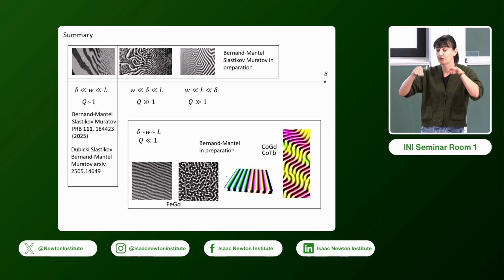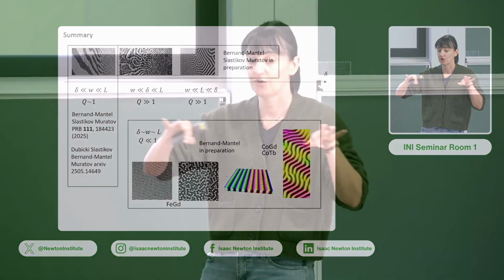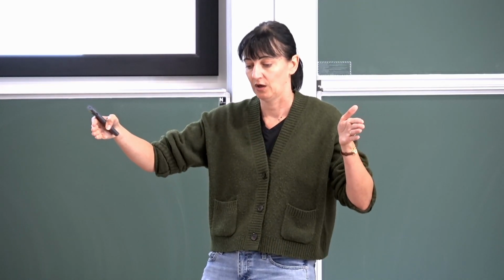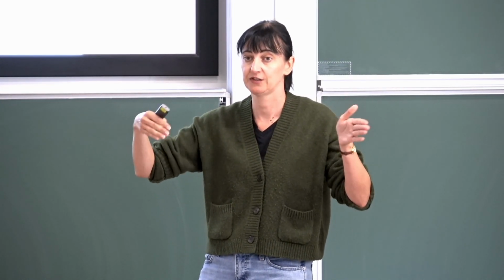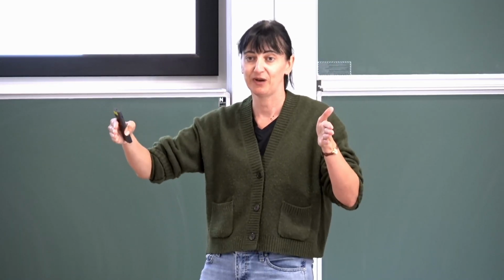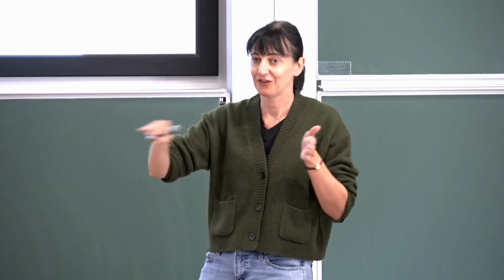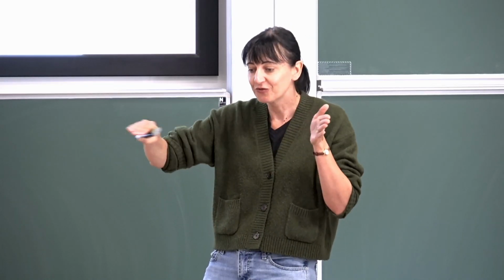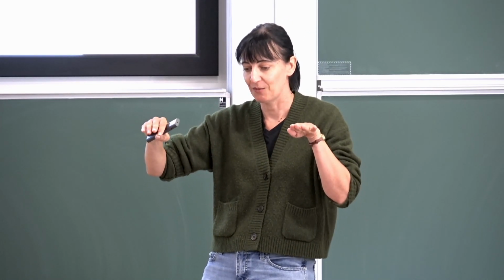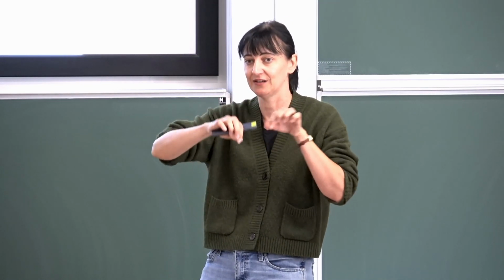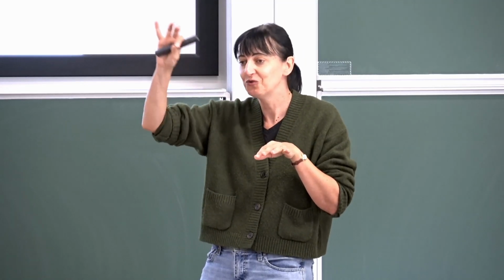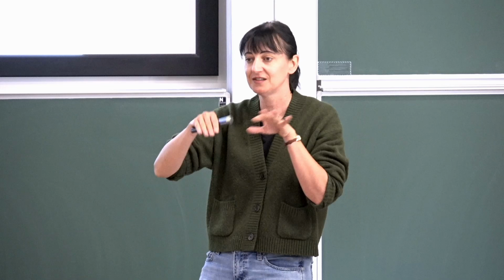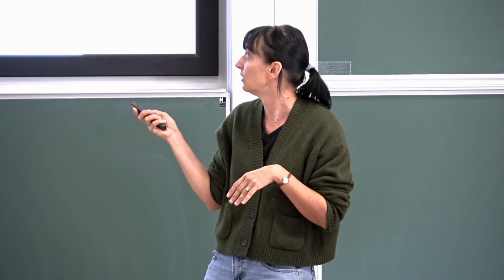But when you have only a few monolayers, there is a lot of disorder appearing because you control the crystallinity in the XY plane. But in the Z direction, unlike the van der Waals magnet where you can really put one layer, two layers, you are growing one monolayer, but there are always steps and islands. That's why you can tune between one and two monolayers very finely. And this creates some disorder.